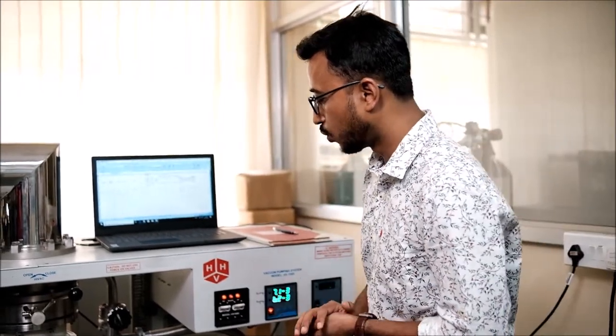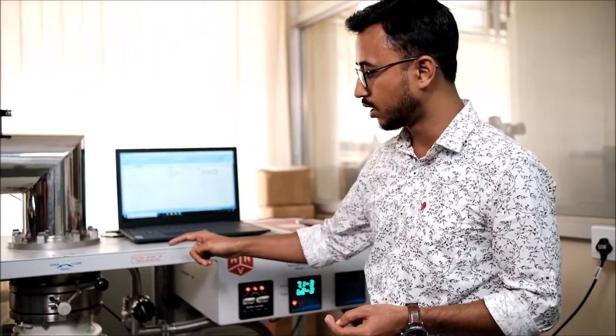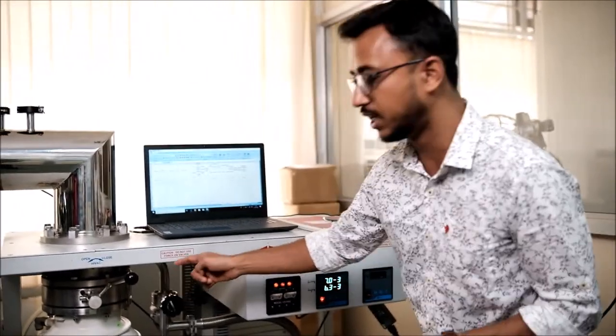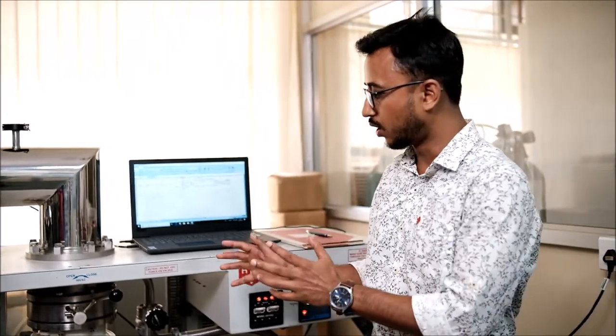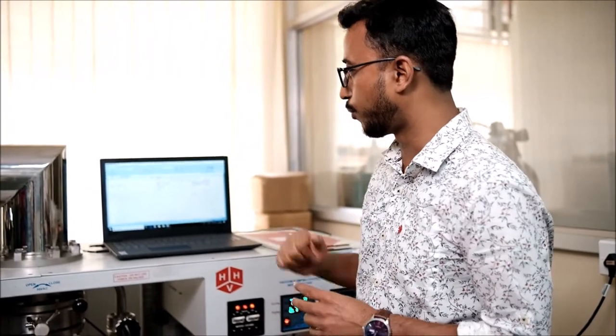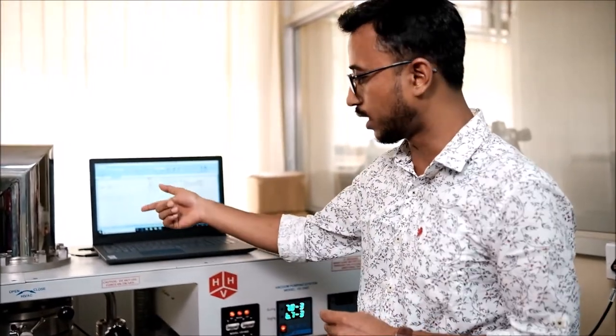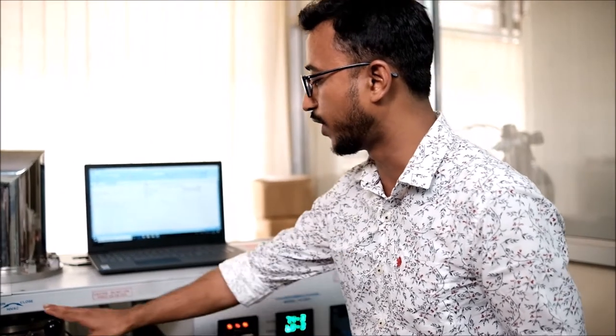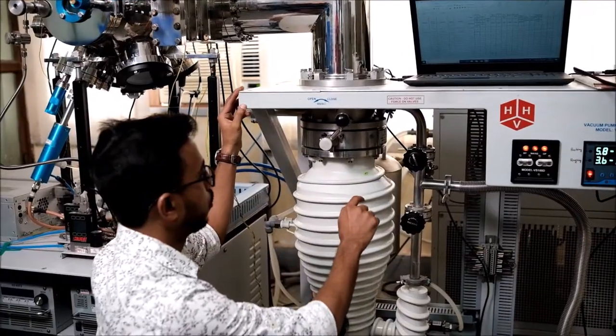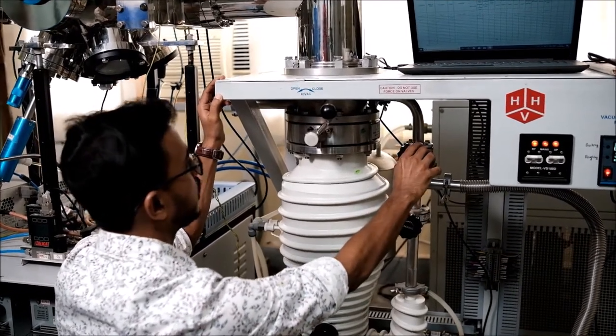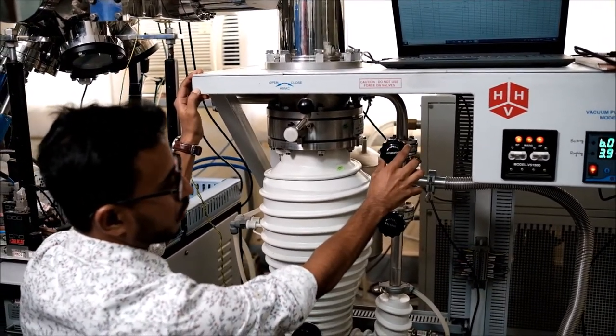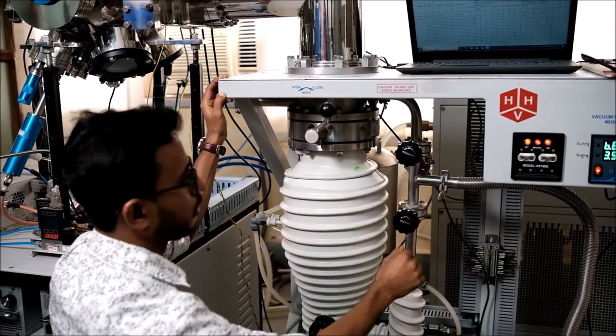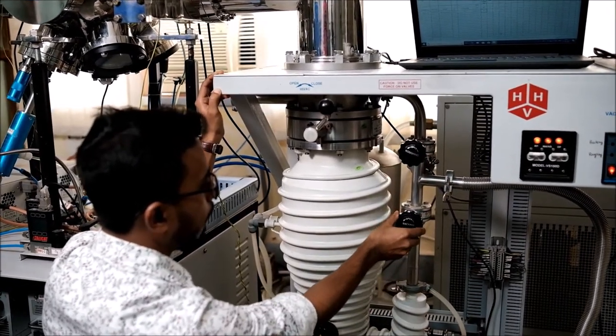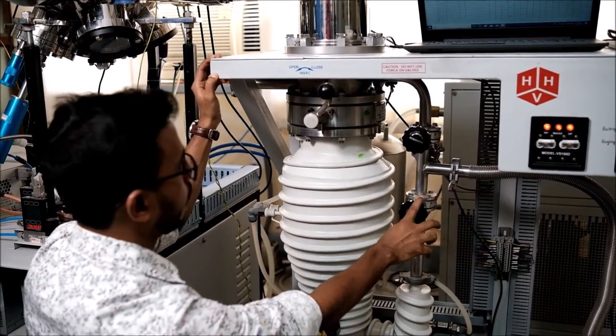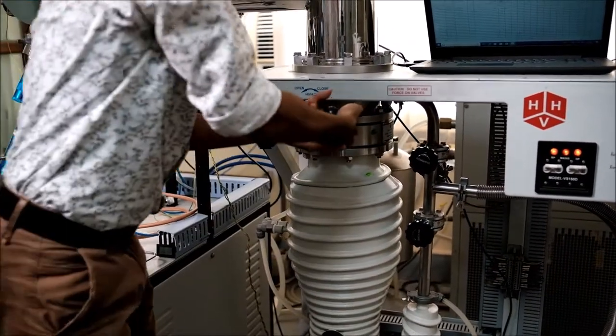So for that we have to first pour liquid nitrogen at the back of a cylinder. This liquid nitrogen works to trap the oil so that it does not go to the chamber and contaminate our deposition. So now we'll pour the liquid nitrogen onto the cylinder, and then we'll turn on the high vacuum valve to connect to the chamber. Here we'll close this roughing valve to disconnect the chamber from the rotary pump, and then we'll open the vacuum valve, and then we'll open this high vacuum valve.